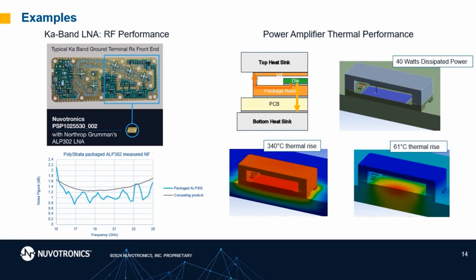So while we're still tuning and optimizing this design, we have been able to show that we can, with Northrop's die, get down to below a 1.2 noise figure floor. There's a lot of jitter in those measured results. I think that comes from the measurement setup, but we're confident in seeing these results to show that we can achieve a very low loss transition from the circuit board to the active device.